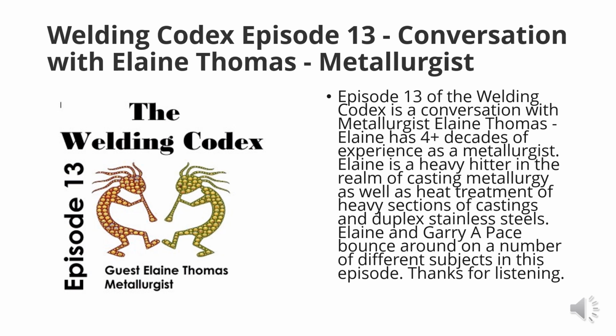I've enjoyed that. So I'm going to go full circle and talk about austenitic stainless steels and sensitization we're worried about there. For those of you that haven't dealt with austenitic stainless steels, if you have your interpass temperatures too high and this time at temperature thing, you're going to get a thing called sensitization, right, Elaine? Correct. For every 6 carbon atoms you've got in the vicinity of the heat affected zone, it's going to take 23 chrome atoms out of commission and form a C6 chrome 23 precipitate on any kind of grain boundary. This makes the area next to the grain boundary be depleted in chrome, and then out in the main grain you've got the regular amount of chrome.